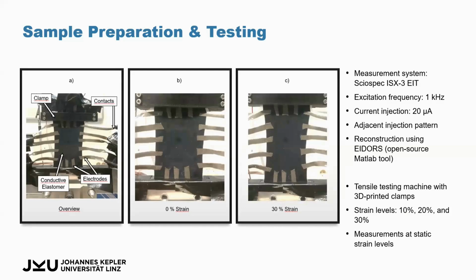The same with the electrical impedance tomography setup, where we have the electrodes on the outside, also very stretchable conductive knit, and the conductive elastomer in the center as the device under test. Now, we use for both measurements a Sciospec, which is actually an electrical impedance spectrometer, but which has an EIT mode. Then we used an adjacent current injection pattern, which is standard, and did the reconstruction in EIDORS, using a Laplace prior, because we assume that the resistivity doesn't change too much.